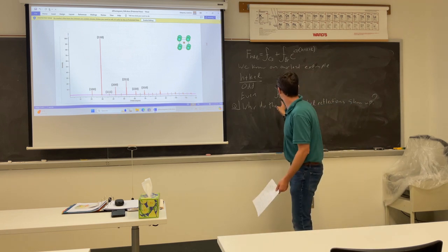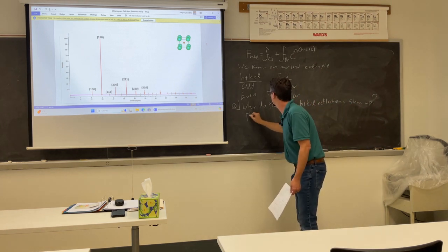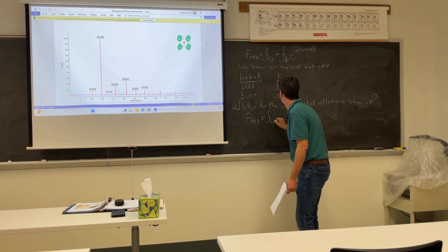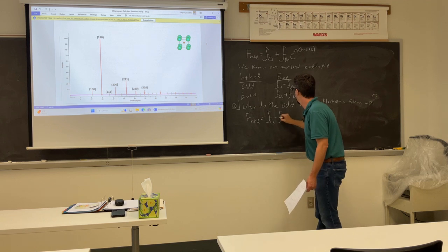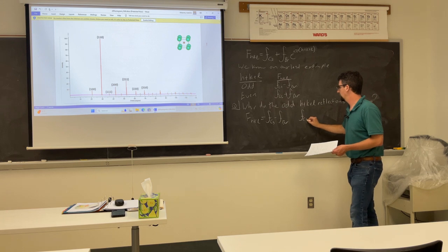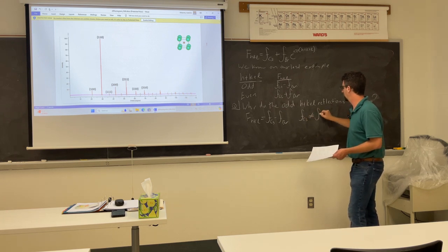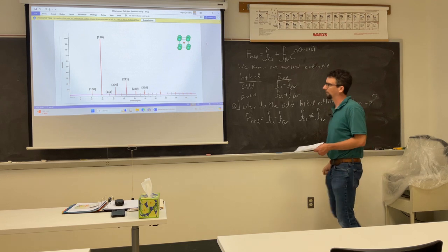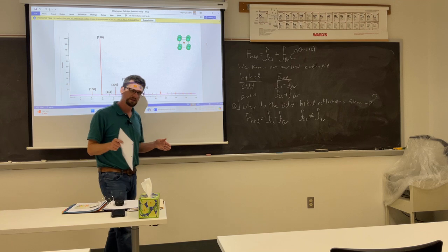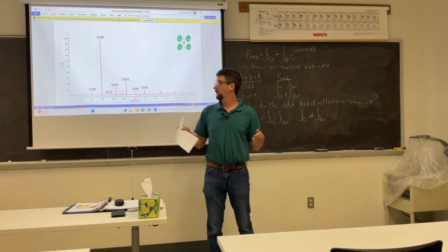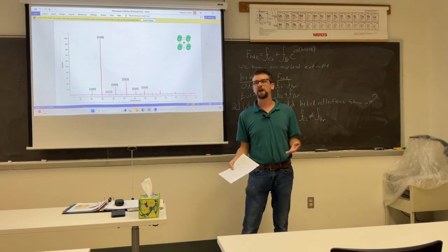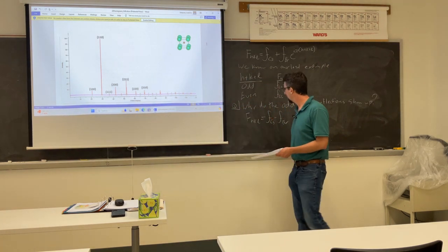And really, the answer to that is the structure factor at these points is equal to the atomic scattering factor of cesium minus the atomic scattering factor of bromine. And we know that these two things are not equivalent to one another. However, the closer that they get to one another in terms of electron density and electronegativity, we will start to see these reflections fade. So the more similar the atomic scattering factors, the less pronounced those reflections will be.